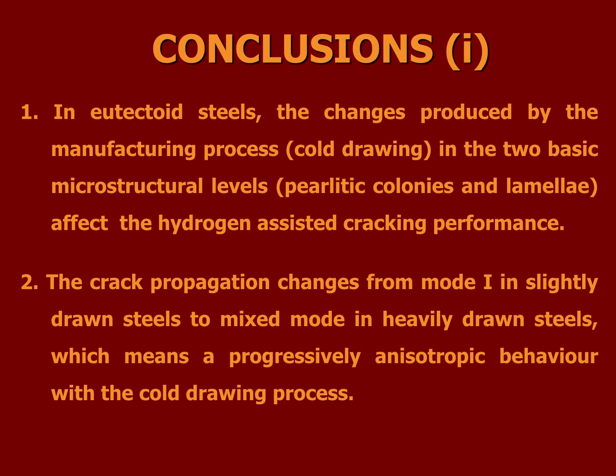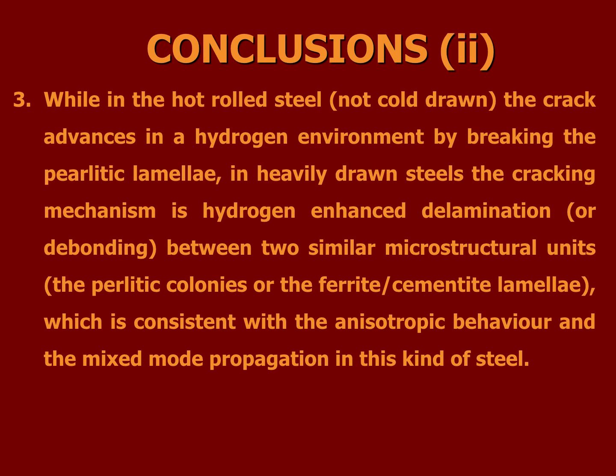Let's go to the conclusions. In eutectoid steels, the changes produced by the manufacturing process, cold drawing, in the two basic microstructural levels of pearlitic colonies and lamella affect the hydrogen-assisted cracking performance. The crack propagation changes from mode 1 in slightly drawn steels to mixed mode in heavily drawn steels, which means a progressively anisotropic behavior with the cold drawing process.